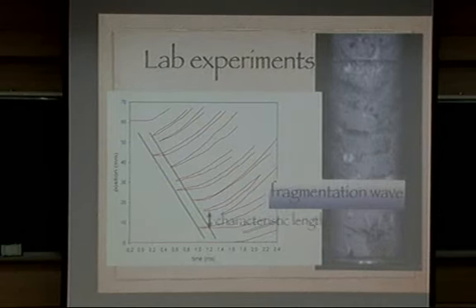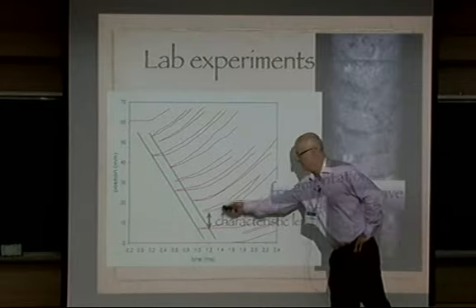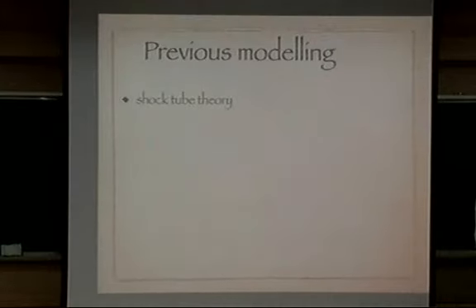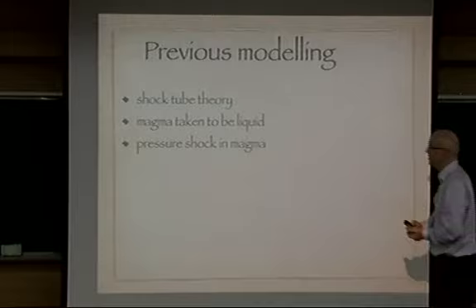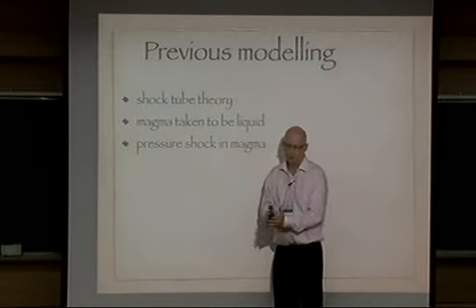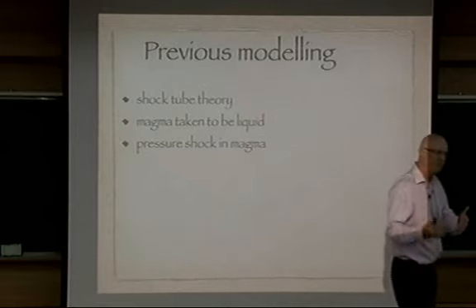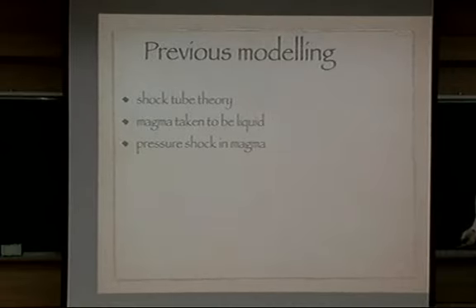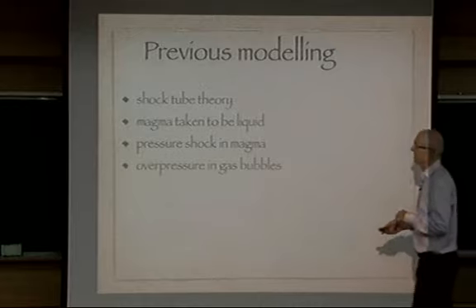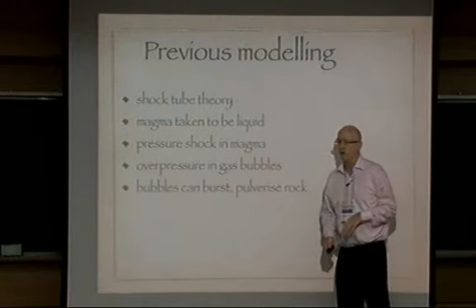Fragmentation wave goes through, and there's a characteristic length scale seen in the experiments. The previous modelling uses something called shock tube theory, which assumes the magma is not solid. In these experiments it is solid, but they take it to be a liquid or even a gaseous mixture, with a rarefaction wave, not really a shock but a pressure drop, propagating into this mixture. That's the theory behind this, and the overpressure in the gas bubbles can burst and pulverise the rock.